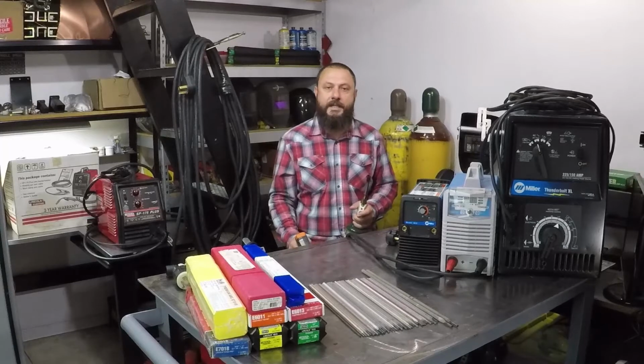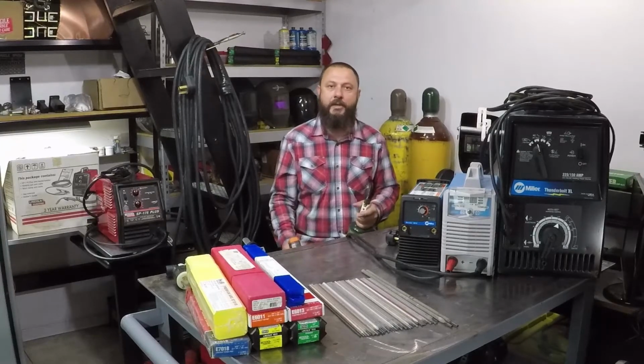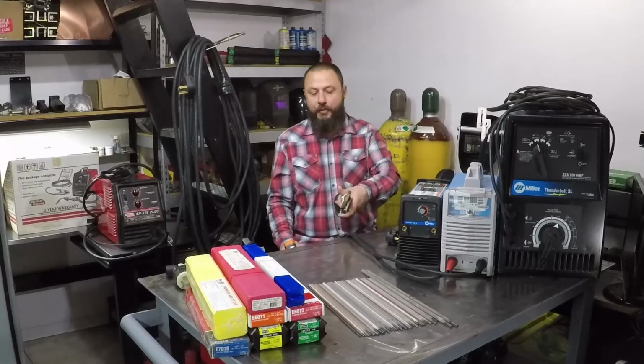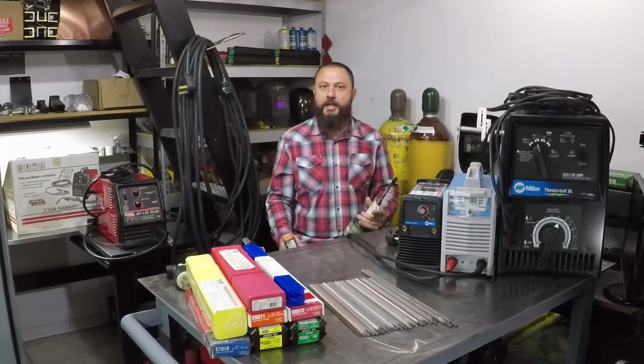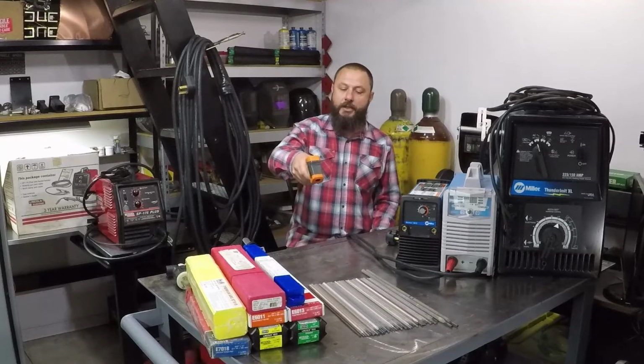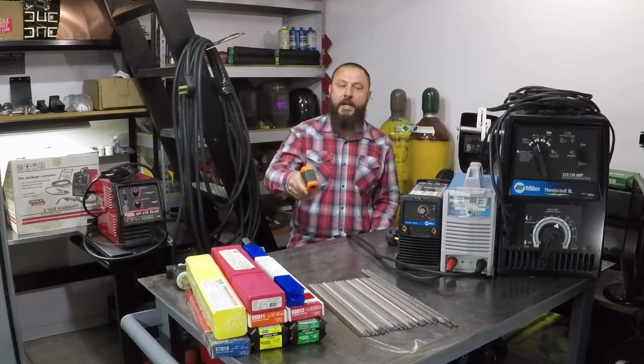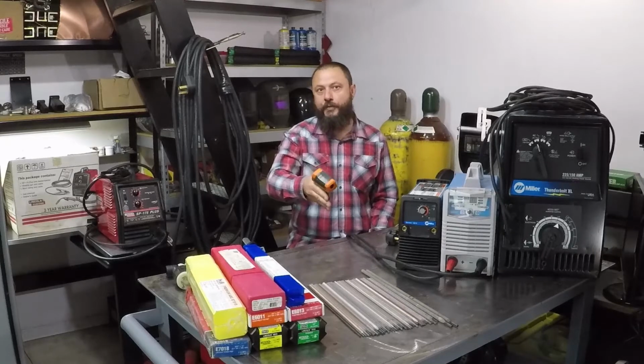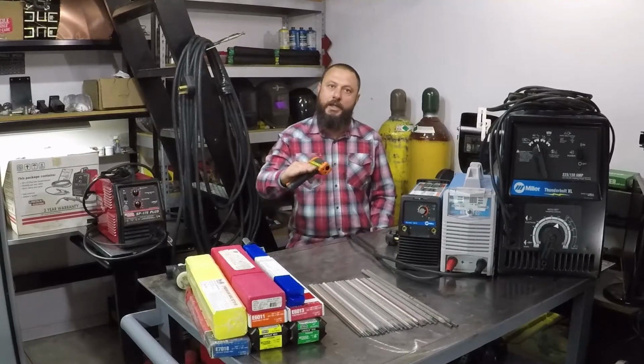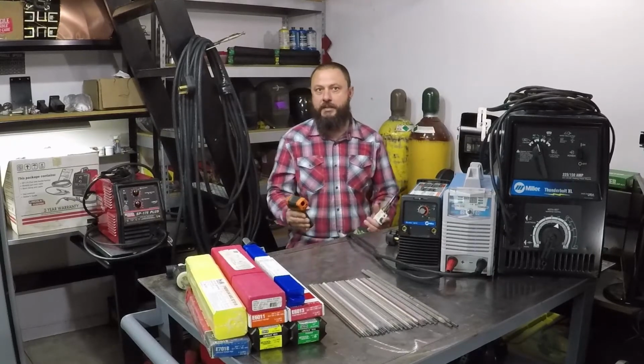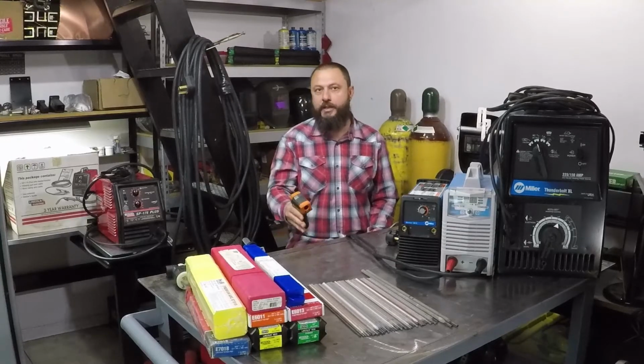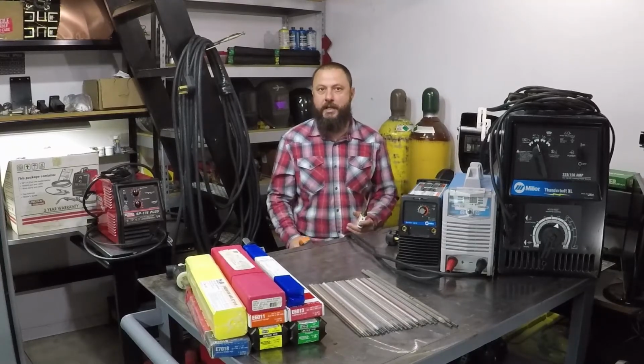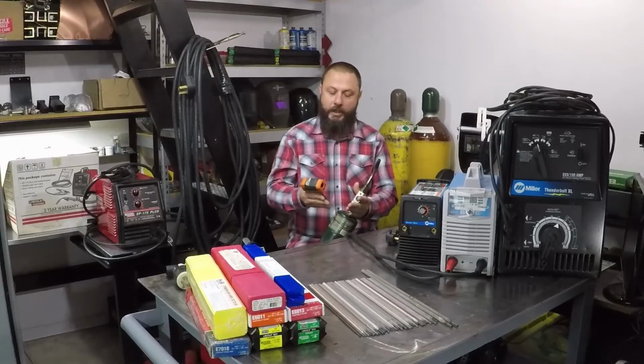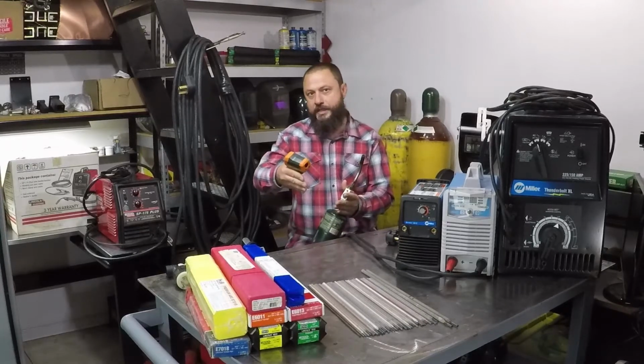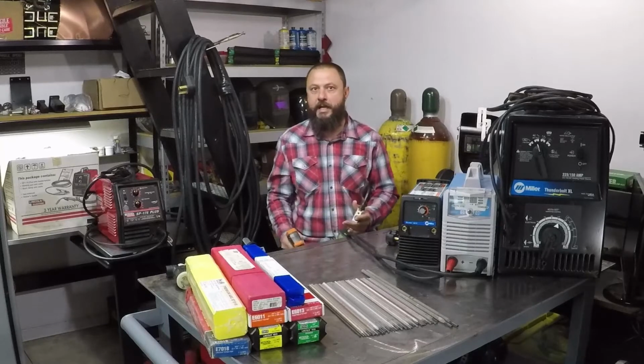When it comes to cast iron, you could also buy a cast iron rod to do any cast iron repair. For that, you have to preheat the metal to a certain temperature. Keep checking it to make sure you reach that temperature. Once you finish the weld, you need to slowly drop the temperature so the cast iron doesn't crack. You can't cool it right away, or the cast iron will split, and either the weld will crack or it will crack on the side between the bead and the cast iron itself.